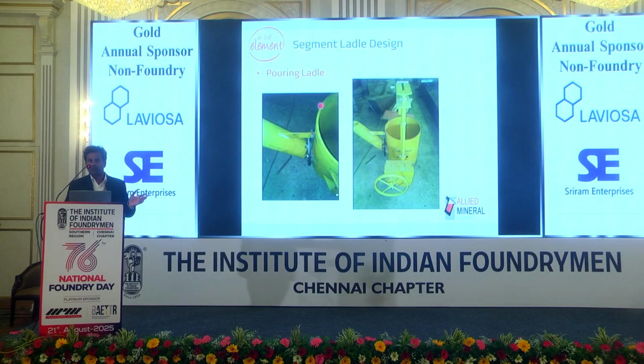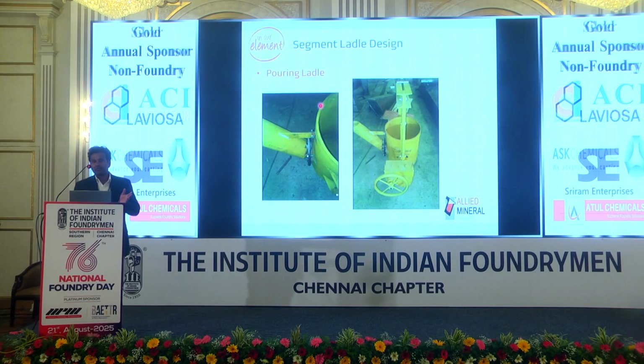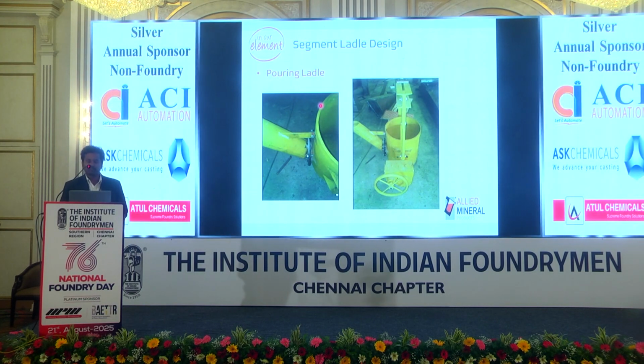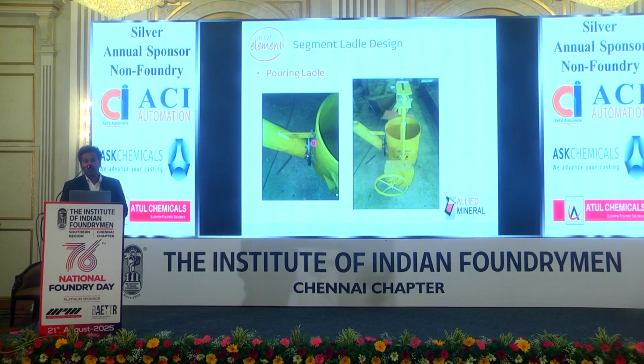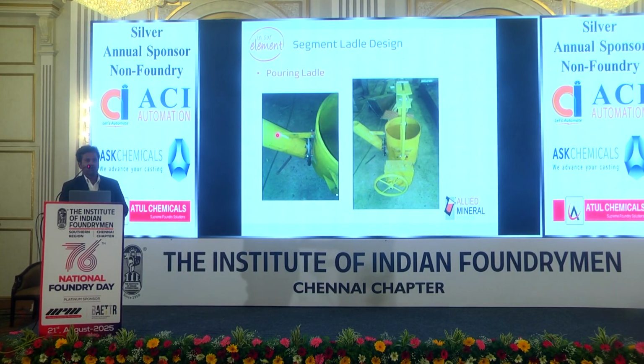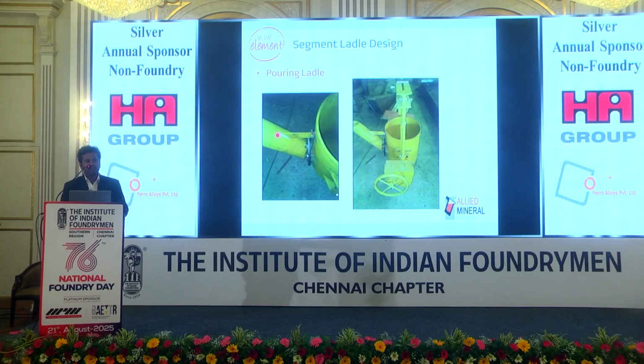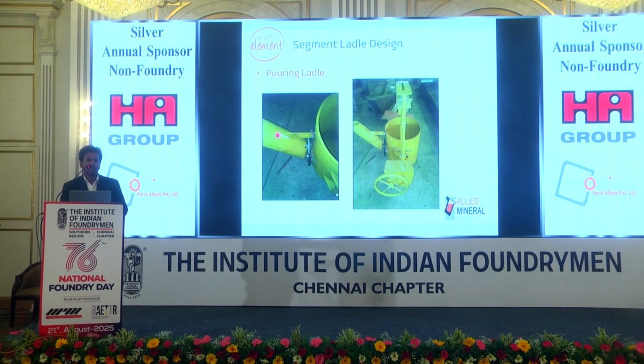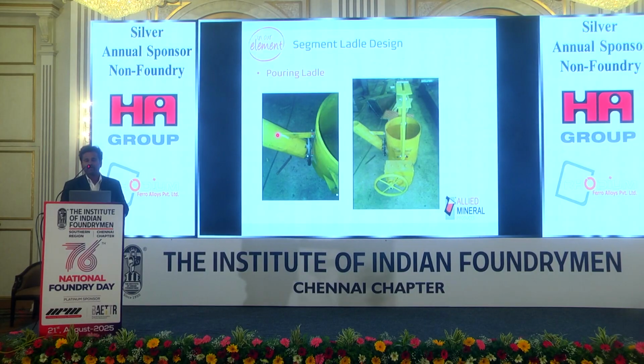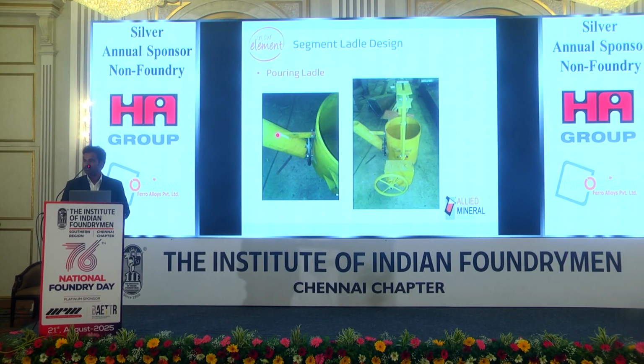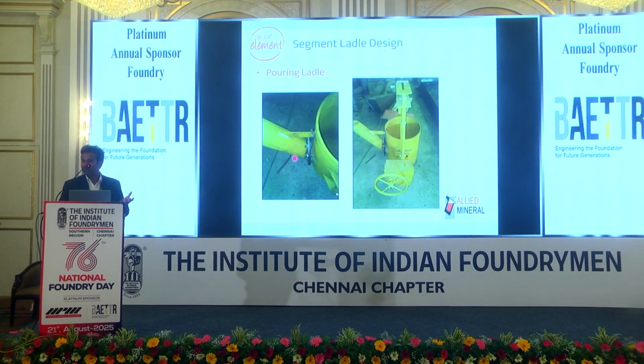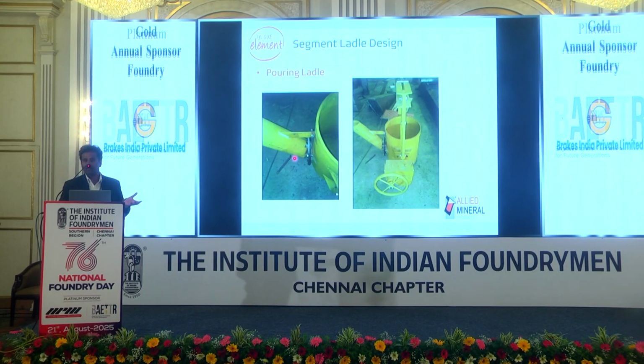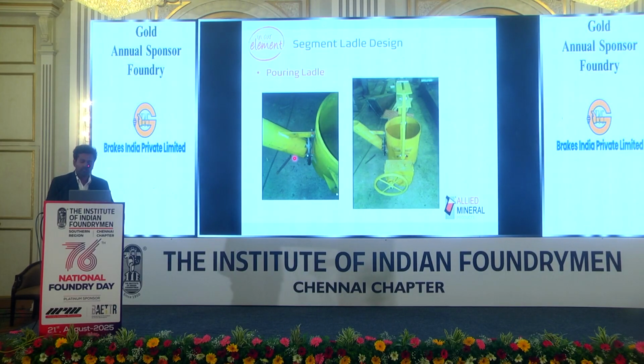And the same system for your pouring ladle. A major bottleneck comes when you use the castable system in your pouring ladle, because your spout diameter will always be smaller to have a better heat loss. But this smaller diameter of spout always has a chance of getting clogged either by slag or solidified metal. You can have a spare spout whenever there are other issues happening. You can just remove and attach the new spout and go.